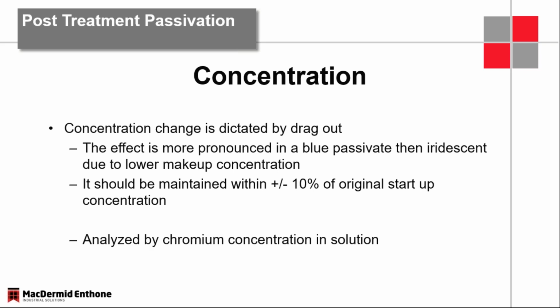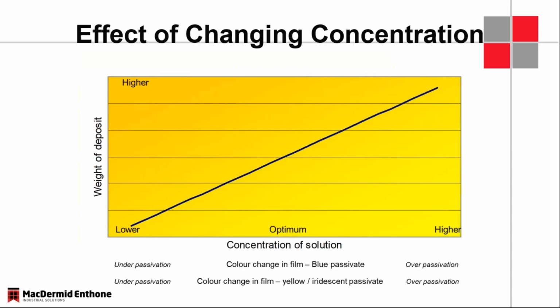And they can be analyzed by chromium content. So you can titrate for it. You can use AA, you can use ICP, and then get a relative concentration based on that. You can do that on the benchtop. Similar concentration changes, lower concentration versus higher concentration. So the higher concentrations are going to produce a thicker film. Lower concentrations are going to be a thinner film, and you're not going to have the color change, and you're not going to have the chrome precipitation reaction that you're looking for.